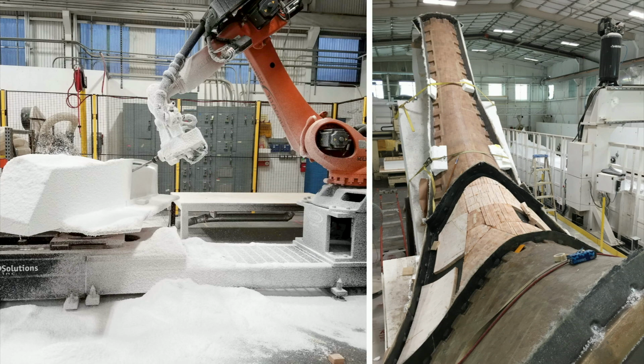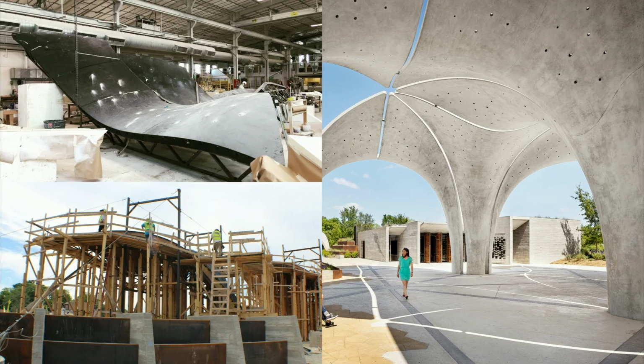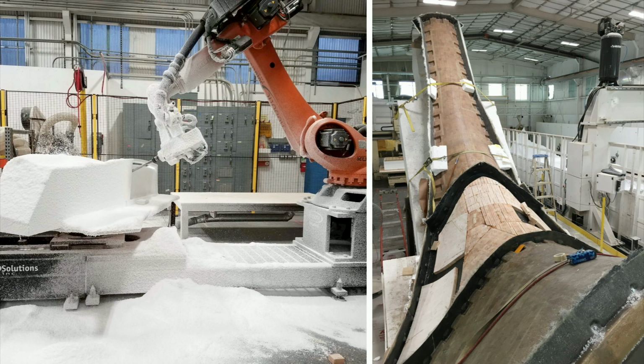The three formwork modules for the A, B, and C petals were fabricated off of 5- and 7-axis milled EPS foam forms. After milling the forms, a 2-inch thick composite structure composed of inner and outer layers of fiberglass composite with a central core of balsa wood was applied. So basically, about an 1/8 of an inch of fiberglass was laid down on top of the foam form, and then this calendared balsa wood was laid over that, which could accept double curvature, and then another layer of fiberglass on the back to produce kind of a monocoque shell.